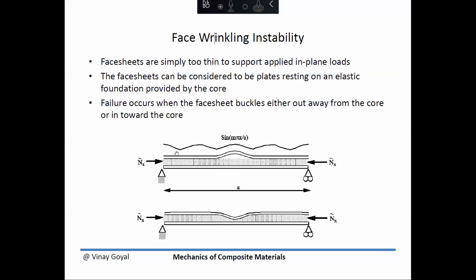You can see here that if you have a sandwich structure with facesheets that are fairly thick and you apply compression loading, it's unlikely that this facesheet will pull away like that or push into the core like that. But it could happen if you have thin laminates.